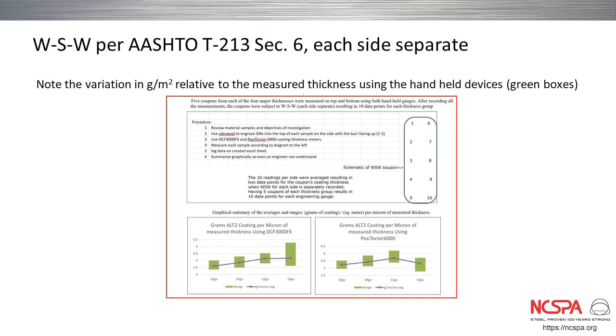The graphical representations present on this slide show the variation that exists when we took 10 measurements per side per coupon and ran the weigh strip weigh data. We would get a final math shakeout of a 3.36 to 4.01 grams per square meter of coating per micron of measured thickness. I say that slowly, but that's grams per meter squared per micron of measured thickness. That's a pretty big window, and you can understand why we don't see these as umpires, but rather guidelines.